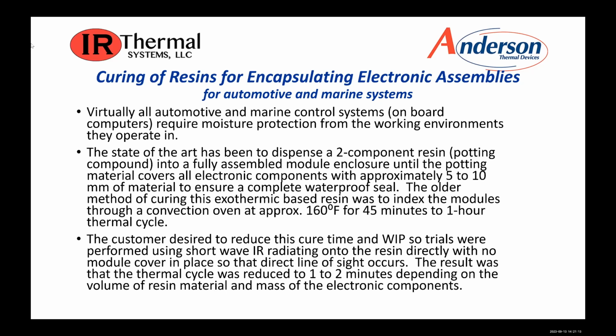We are able to actually have line of sight, and utilizing a shortwave infrared emitter at about 1.7 or let's say 1.8 microns. If we go back to the earlier part of the presentation, you remember looking at those absorption curves, we find that the polyurethane was very transparent to the infrared at this level. Therefore, the infrared energy was able to pass through the polyurethane and be absorbed by the circuit board and the components. It would elevate the components and the circuit board to approximately 130 to 140 degrees Fahrenheit, whereupon this additional heating was able to speed up the resin, the 2-component resin, which is an exothermic-based cure, meaning that the